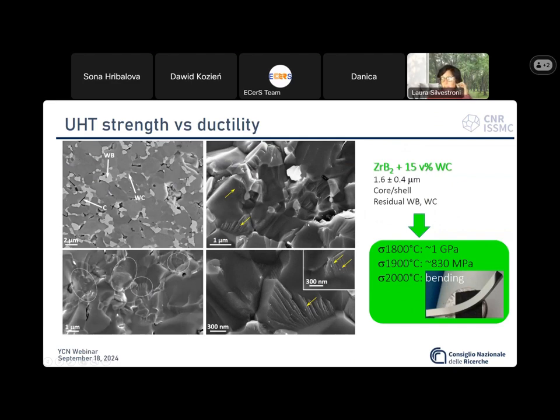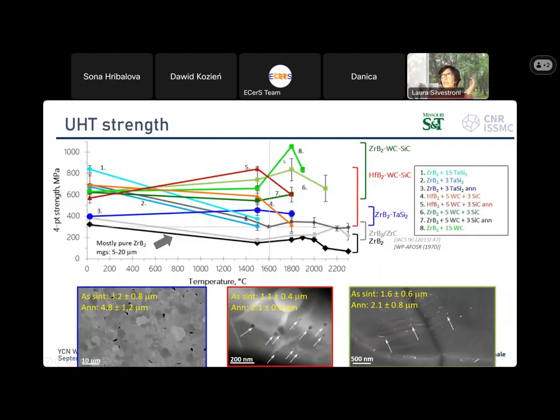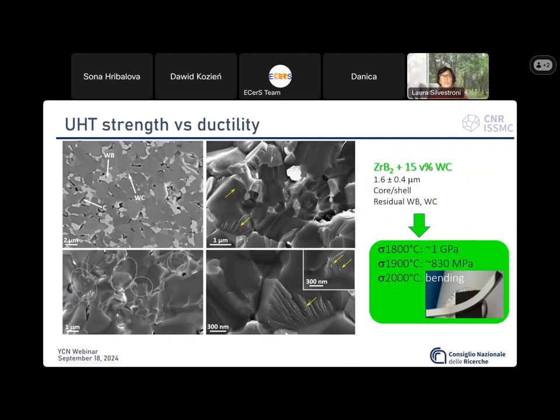The highest strength was found for this fluo green here, that belonged to a zirconium diboride material, where the addition of tungsten carbide was increased to 15 volume%. And this composition resulted in an unprecedented strength of 1 gigapascal at 1800 centigrade that remained over 830 up to 1900 degrees C. Moving beyond this temperature, the ceramic underwent plastic deformation that we attribute to the ductility of the dispersed tungsten boride phase and the approach of the eutectic temperature. Anyway, we didn't have a brittle failure.